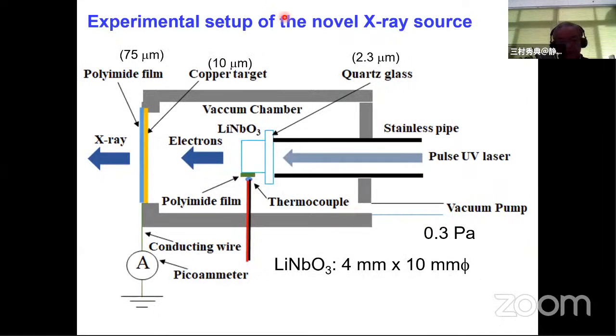This slide shows the experimental setup of the novel X-ray source. We use a copper target and a cylindrical lithium niobate pyroelectric crystal. The size of the lithium niobate is 4 millimeters in length and 10 millimeters in diameter. The pressure inside the vacuum chamber was 0.3 Pascal. We detected X-rays with an X-ray detector and measured the temperature of the lithium niobate crystal with a thermocouple.